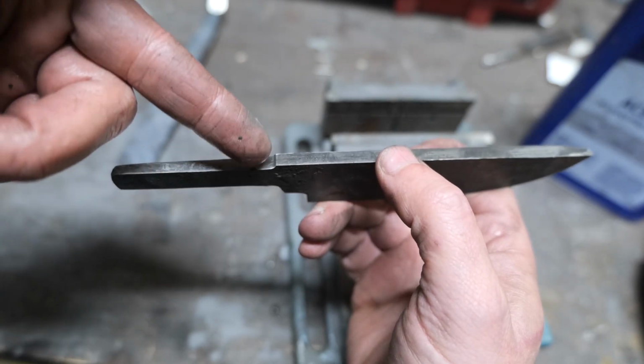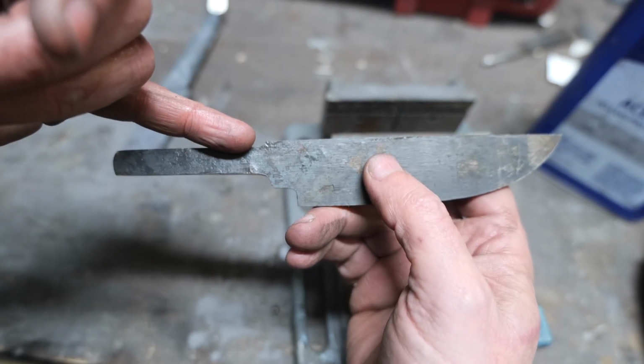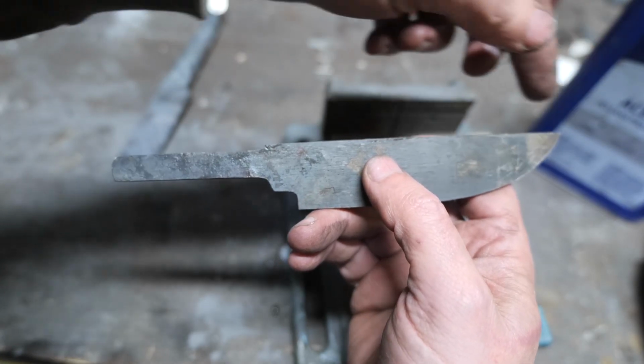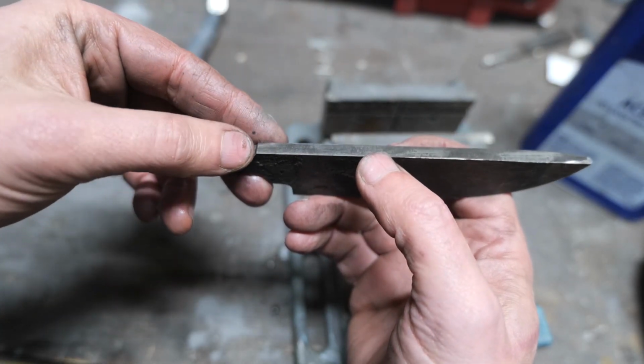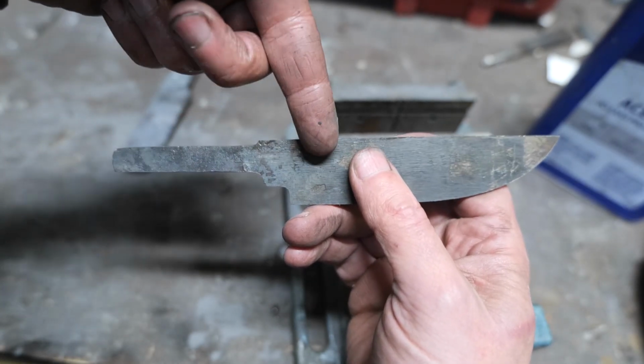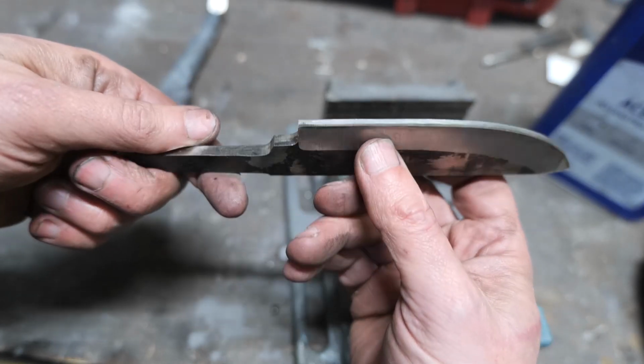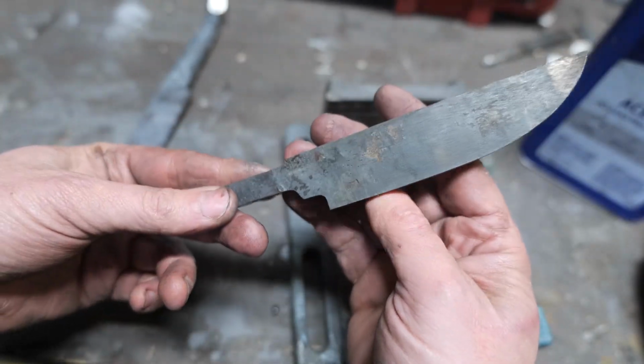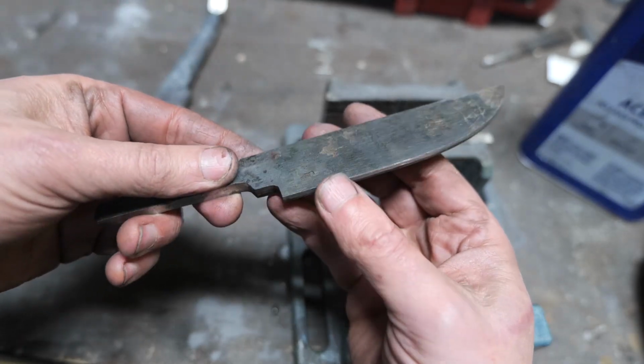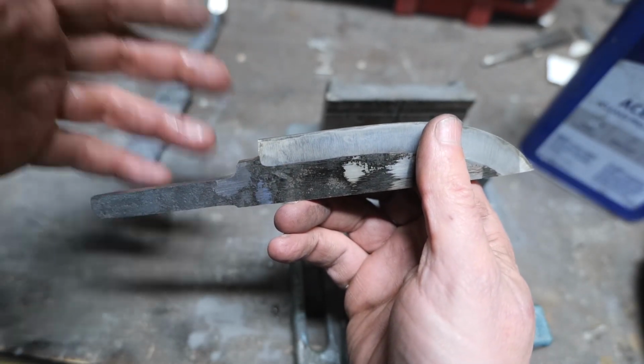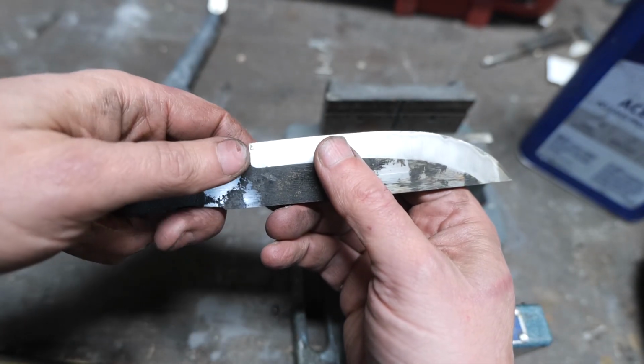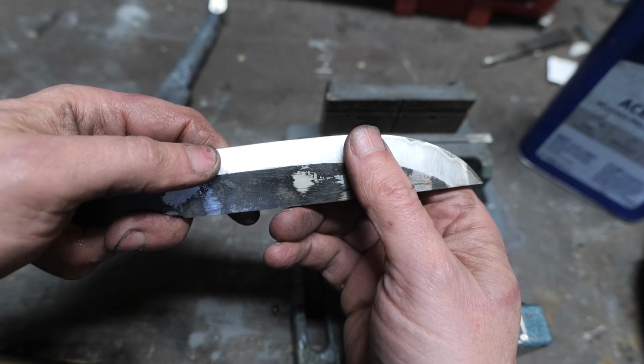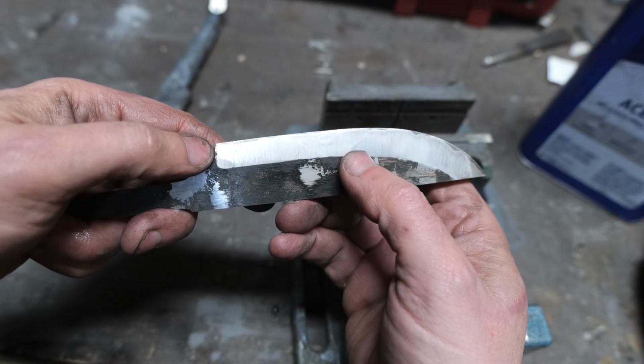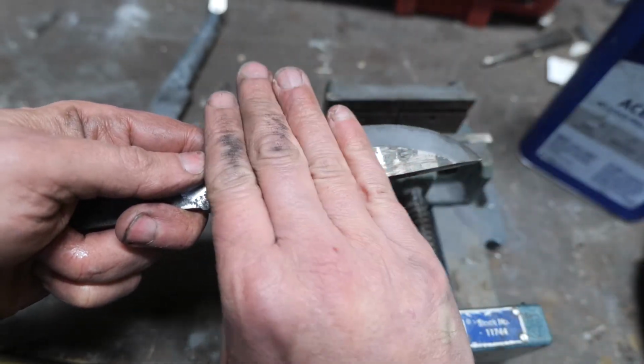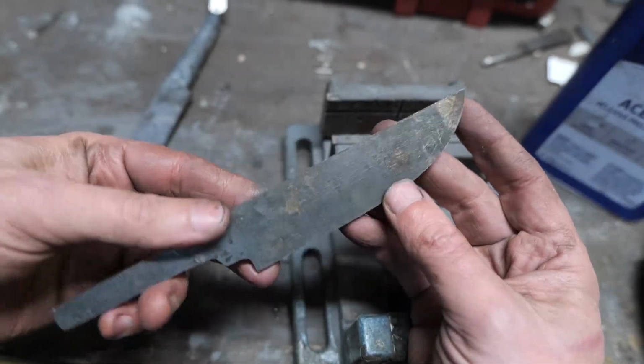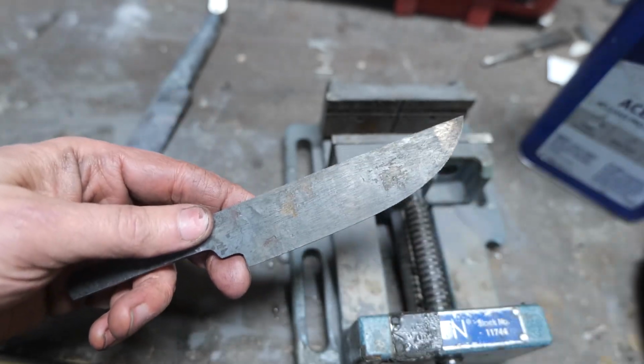And that weld being bad makes me wonder about the other welds too. To be honest, having some bad welds around the very edge of your billet, I can understand that, but when they're deeper into the middle part of what was the billet, then you really have to wonder. So I had to start over. I did the same exact thing, same process, only I got the forge much hotter. I was actually sparking the canister. This canister was falling off and oxidizing and sparking away when I pressed it. So I don't think I was quite hot enough to get a full nice weld with this effort. But the next effort, as you're going to see, turned out just fine.